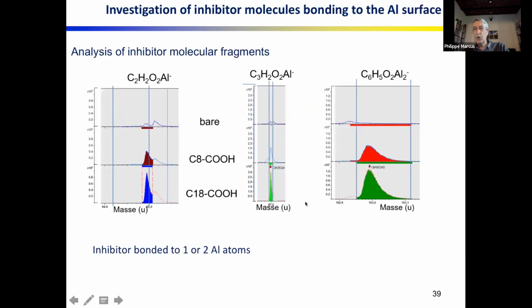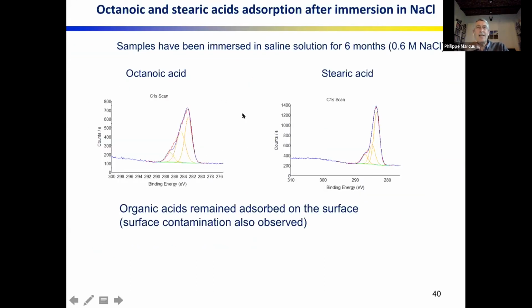With TOF-SIMS, we can get an additional measurement, in that we can look at fragments of the molecules that contain aluminum. Here we looked at a fragment containing one aluminum atom, and here we looked at fragments containing two aluminum atoms. And you can see that if you look at the octanoic acid, we find signals for fragments containing one aluminum and containing two aluminums. And this is also the case for stearic acid. So we can conclude here that the inhibitor is bonded to one or two aluminum atoms. And this is, of course, a key feature: the nature of the chemical bonding of the organic molecule to the oxidized surface.